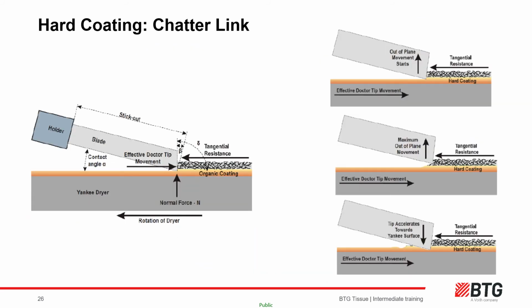And here we can see the steps that lead to chatter when coating becomes too hard. On the left we can see the blade gliding in the organic coating underneath the sheet, so removing some coating and the sheet and crepe structure. This is what we want. The creping doctor linear load is sufficient to comfortably overcome the sheet, the adhesion and Yankee forces, and gently go about its business of refreshing the coating and creping the sheet. Provided the coating remains soft and robust, then it's happy days for any blade material.